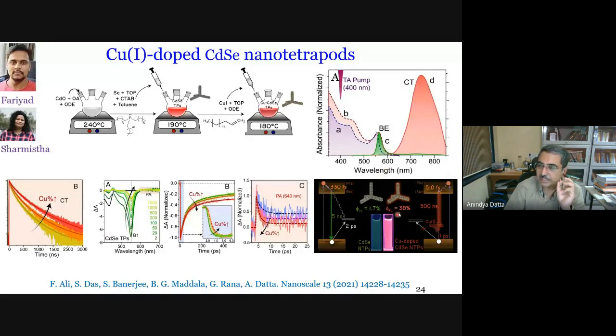In doped nanocrystals, the Cu plus trap, Faryad gets really unhappy if I say trap, so let me use the word he likes. When we add Cu plus, it captures a hole in a matter of 1 picosecond or so. And that is what competes with the relatively slower process of trapping that is there in the tetrapods already. So the reason why it works is that the hole capture, did I say proton? Sorry about that, hole capture. The hole is captured by copper at a faster rate than the inherent hole traps that are there. And it is then the recombination that takes place eventually, that is what is long lived. So that is what we understand about the doped CdSe nanotetrapods so far.